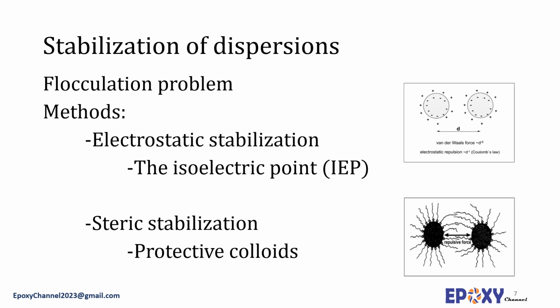However, there is a risk for polymer coiling and subsequently flocculation if the medium is a poor solvent for the polymers, for example. On the other hand, the risk of bridging, flocculations, incompatibility, and high viscosities also exists if the molecular mass of these polymers is too high. The molecular masses of these polymers is often in the range of 1,000 to 15,000.